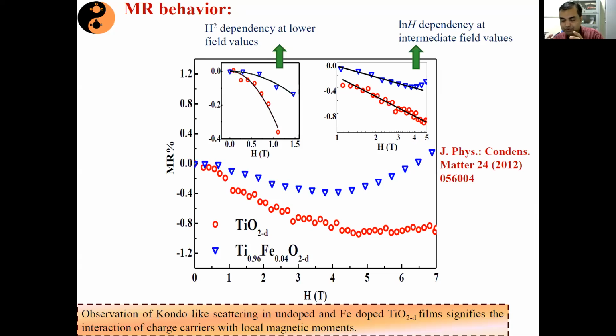So we do resistivity measurement in field and without field. So if I apply a magnetic field, then the resistance changes. That is nothing but the magnetoresistance. Magnetoresistance we define by resistance in presence of field minus resistance in absence of field divided by resistance in absence of field multiplied by 100. So that is our magnetoresistance. So if you look at this particular material's behavior, it shows a finite magnetoresistance behavior. So that means it has got some spin polarized carrier also in the system.